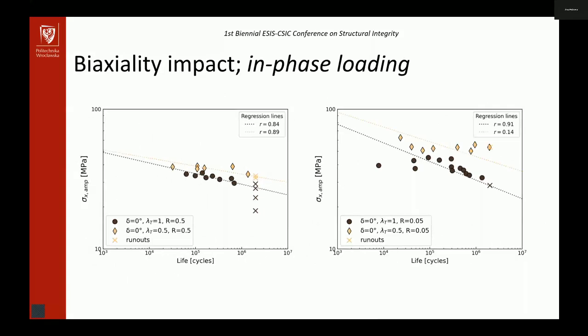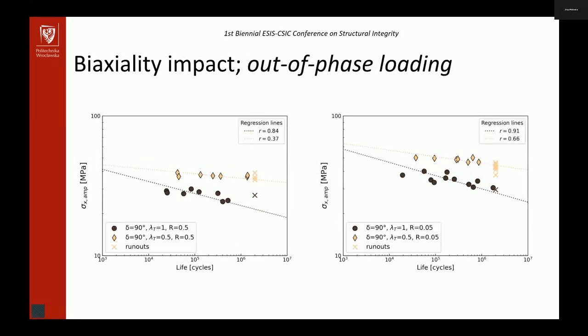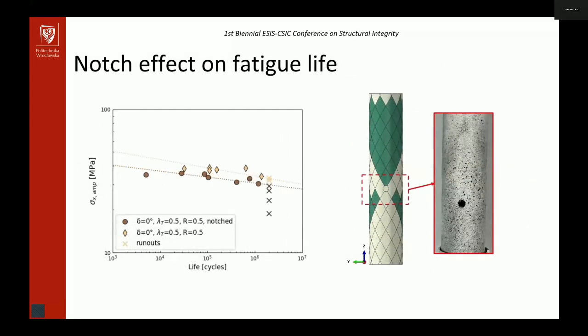I would also like to present the data that I'm currently working on. I'm trying to see the applicability if there are additional parameters which affect the fatigue. So for the lower biaxiality of 0.5, it means the normal geometrical stress is twice the shear. We see the shifting in S-N curves. The same for the out-of-phase loading, and also the notch effect on fatigue life.